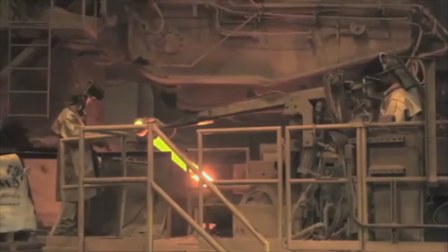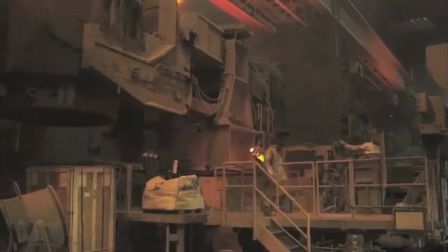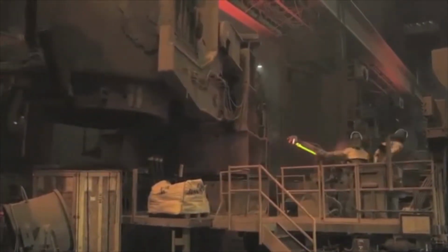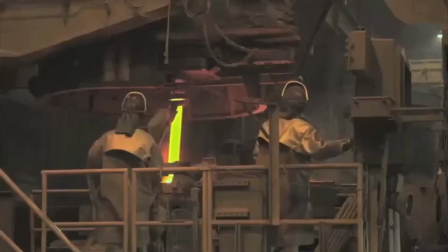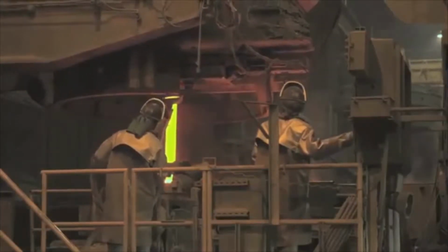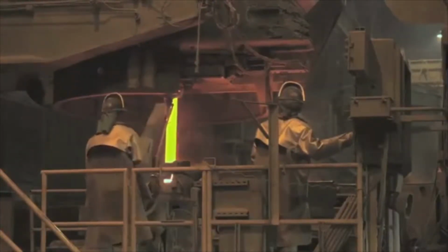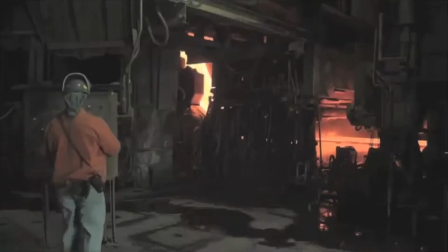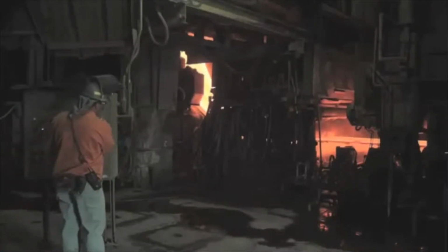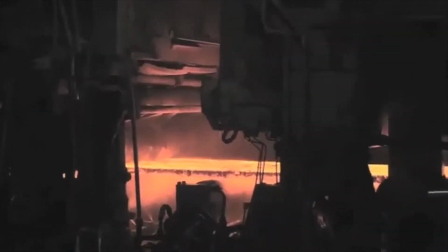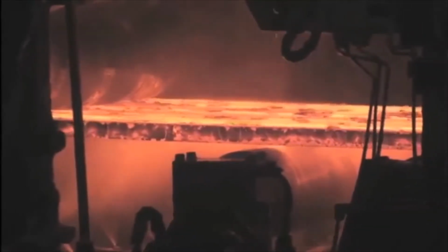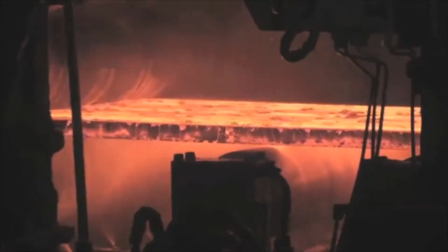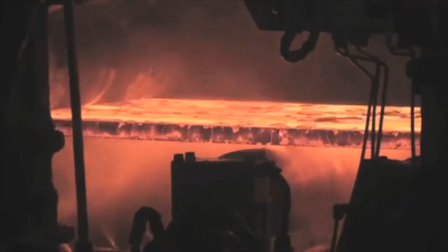On the caster deck, the turret rotates to exchange an emptied ladle with another ladle filled with molten metal. As it goes through the casters, the molten steel, now about 2,800 degrees Fahrenheit, is converted into a continuous ribbon of steel approximately 60 millimeters thick and up to 180 feet long. These thin slabs can be rolled into steel sheet much more quickly, efficiently, and cost-effectively than the much thicker slabs produced at traditional integrated steel mills.